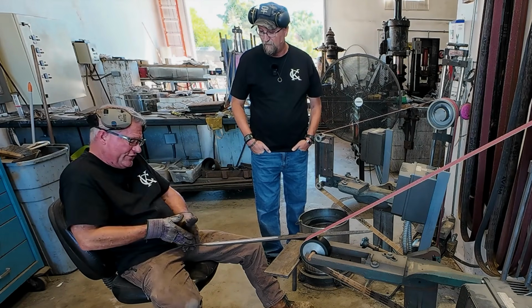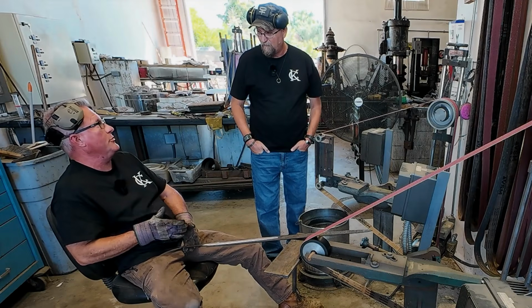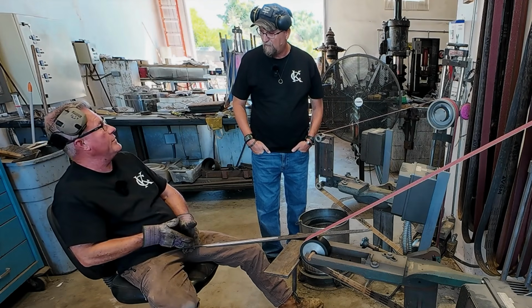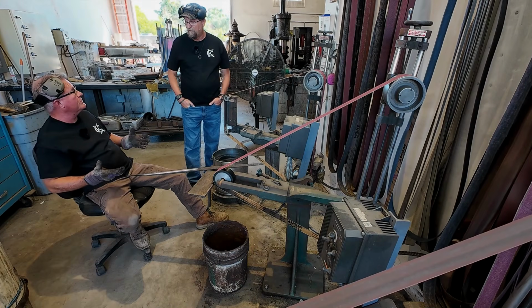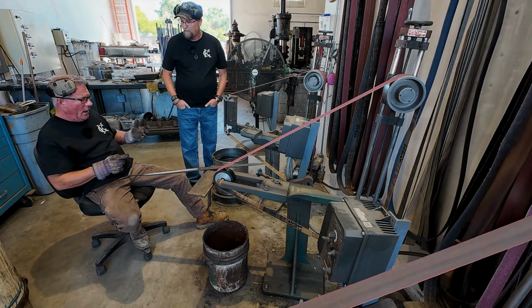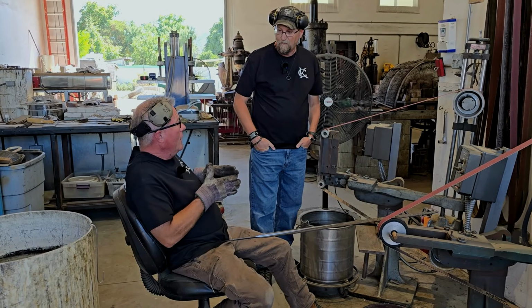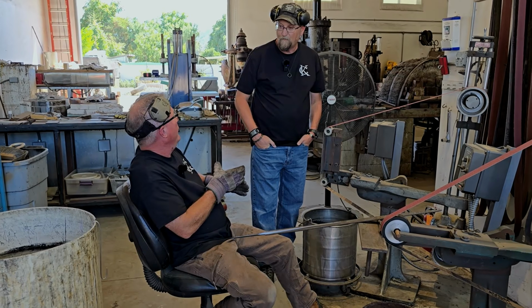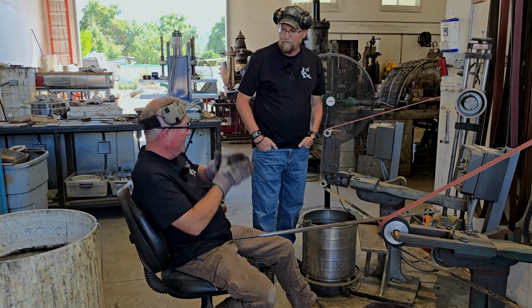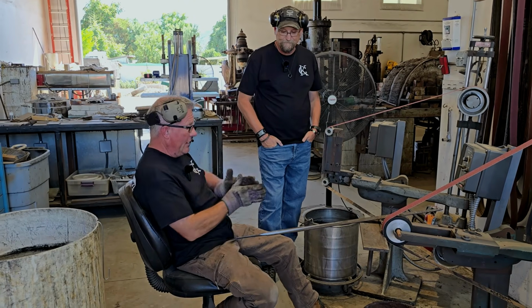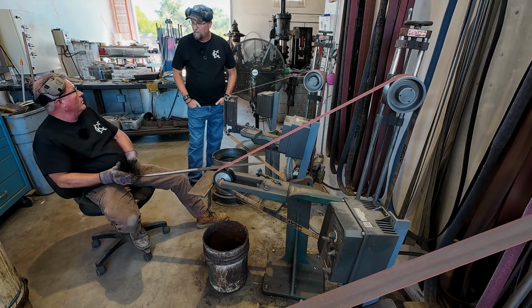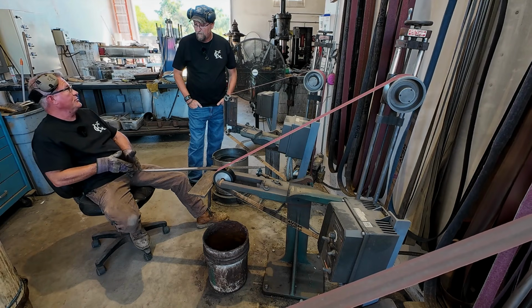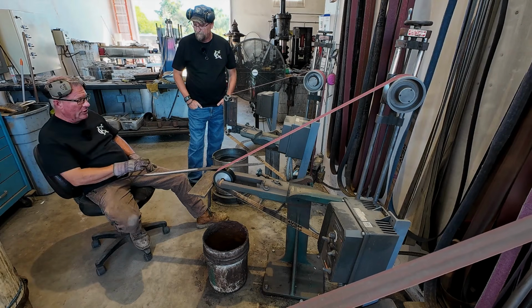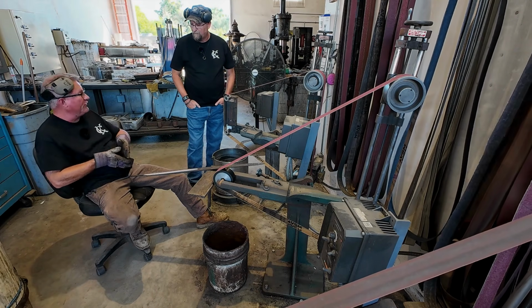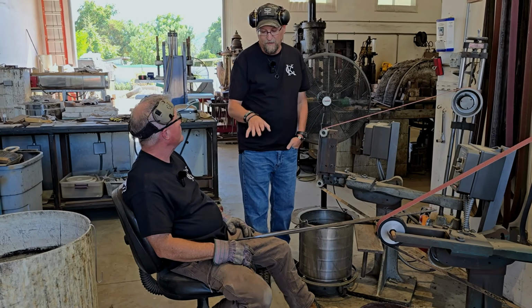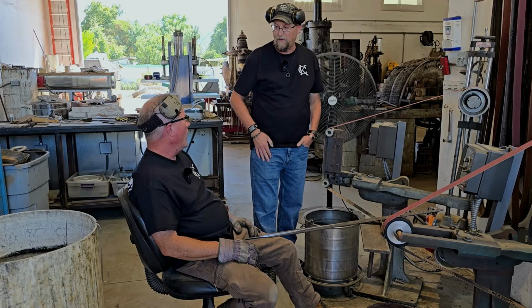Okay. So they forged that typically, not always, sometimes they ground them in, but they always ran it into the tang. If you look at traditional ancient swords, Viking age, even Roman, you see the fullers, and you see the gap that fits the guard. Right. There's usually a gap there, and that's because the fuller runs into the tang. They did it basically to widen the whole piece out. So you're forging the fuller in, and also forging it into the tang. From a lot of examples I've seen, yeah, they forged them in. So does that affect the strength of the tang blade joint at all? I don't think so.